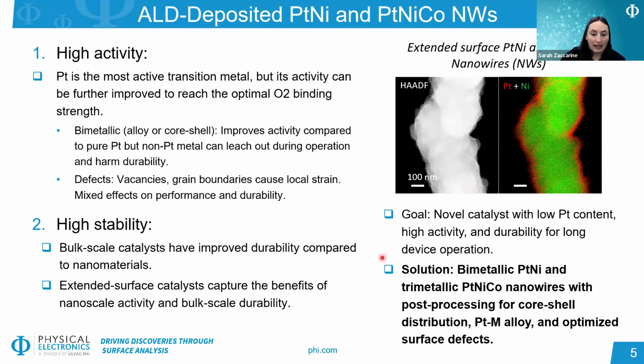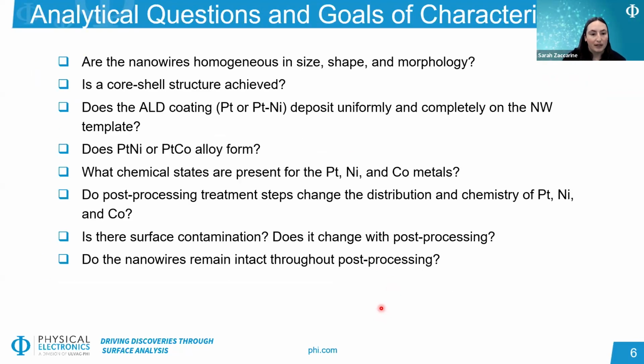And these were treated with a couple of different post-processing steps, including annealing to develop an alloy to improve the activity of the platinum, as well as a pre-leaching step to pull out some of that excess transition metal to achieve better durability. So throughout this talk, we're going to be talking about these two different sample sets and the different post-processing steps that were used to improve both activity and durability for these types of applications.